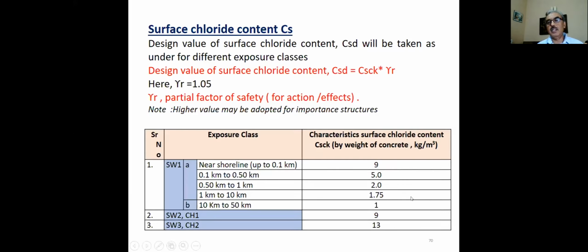This 1 kg is quite close to 0.6, which we are permitting in any case as an initial chloride in the concrete itself. At this level generally corrosion does not occur in many cases. So that is why we say when we go to this level, we check it for carbonation also, since carbonation may be more critical here.